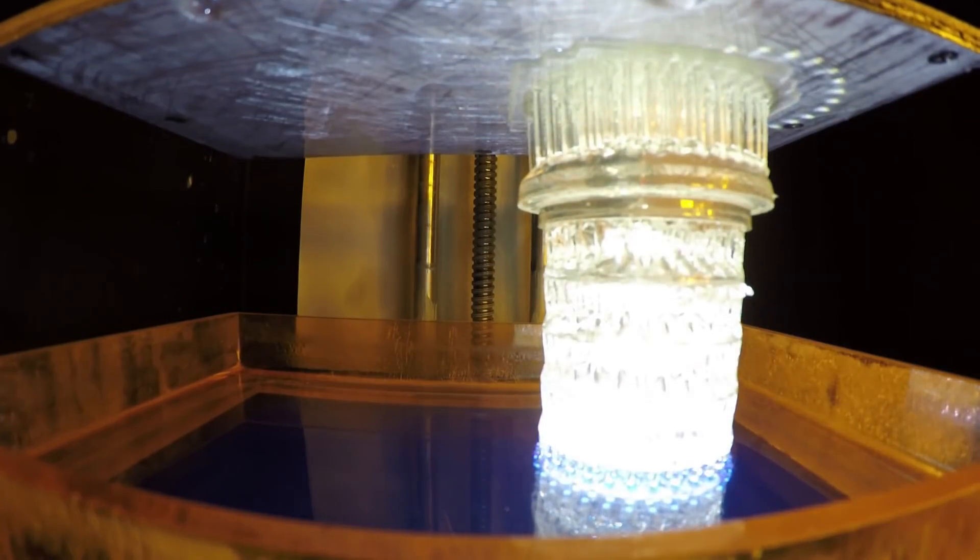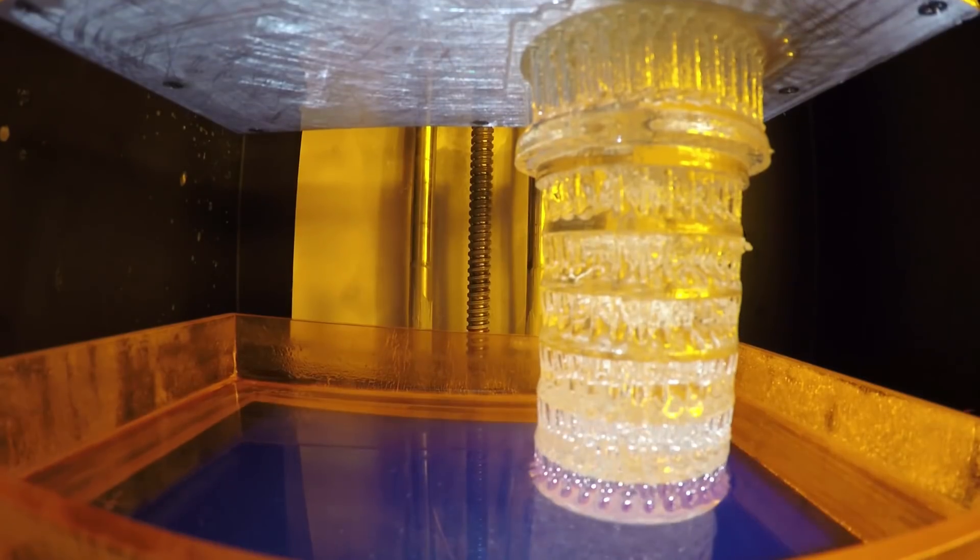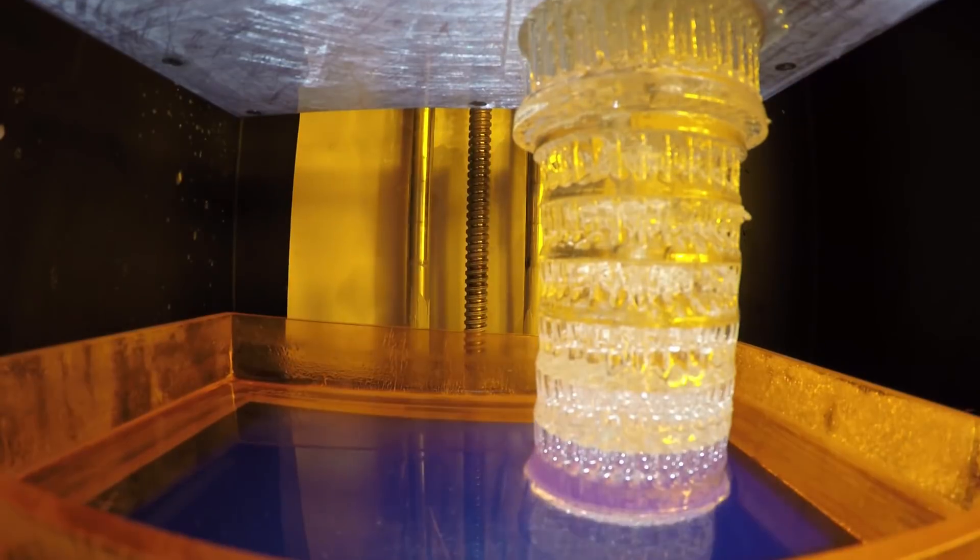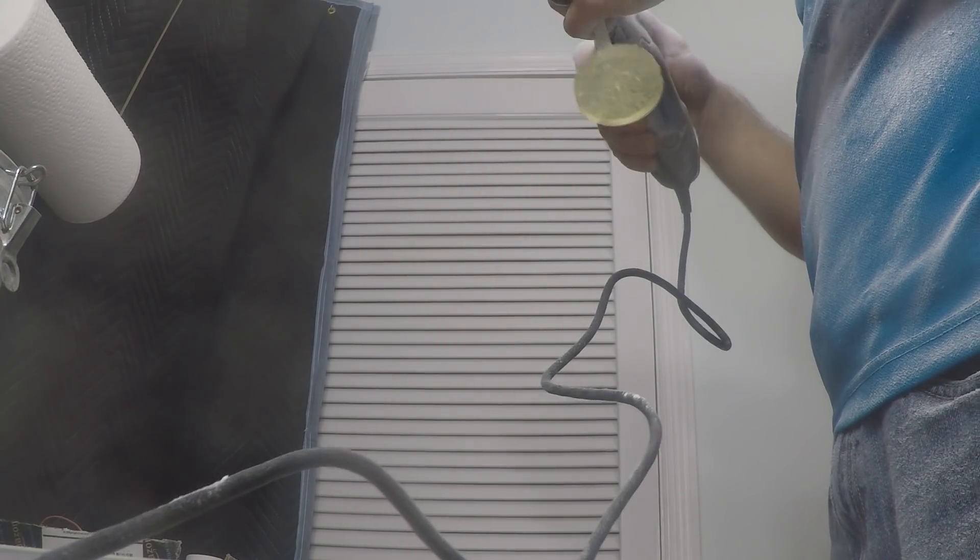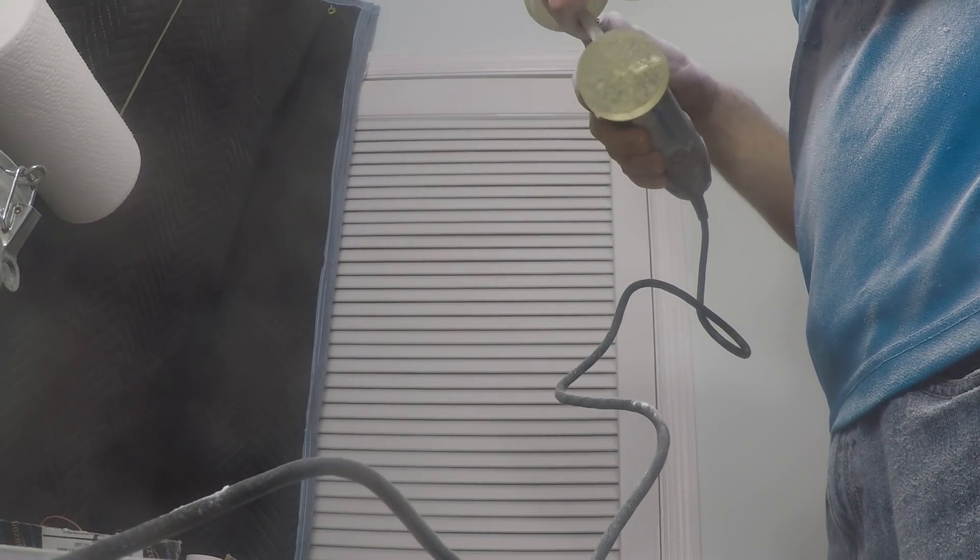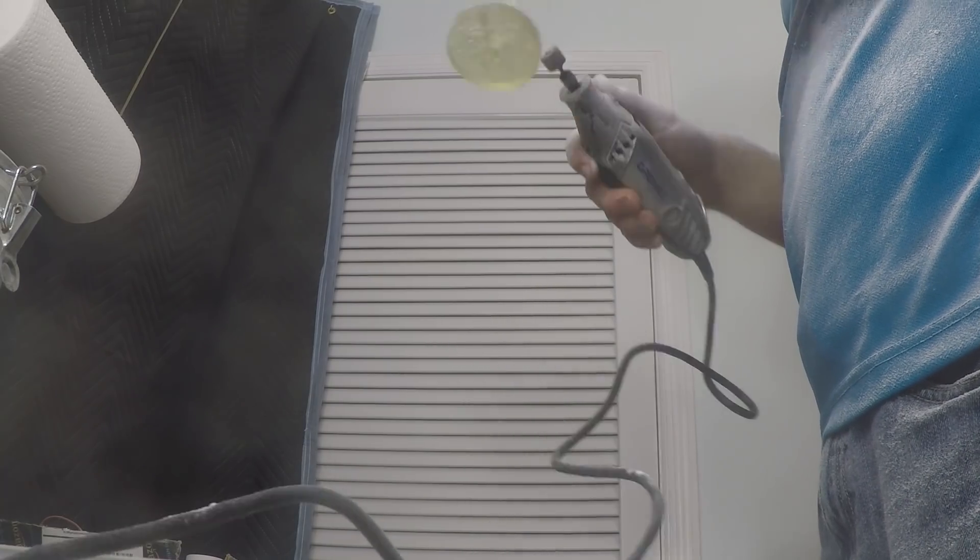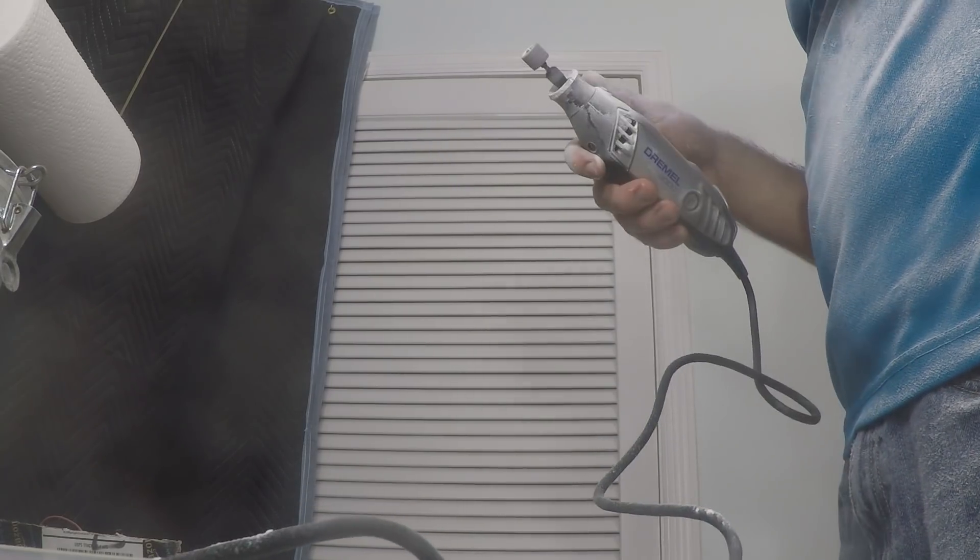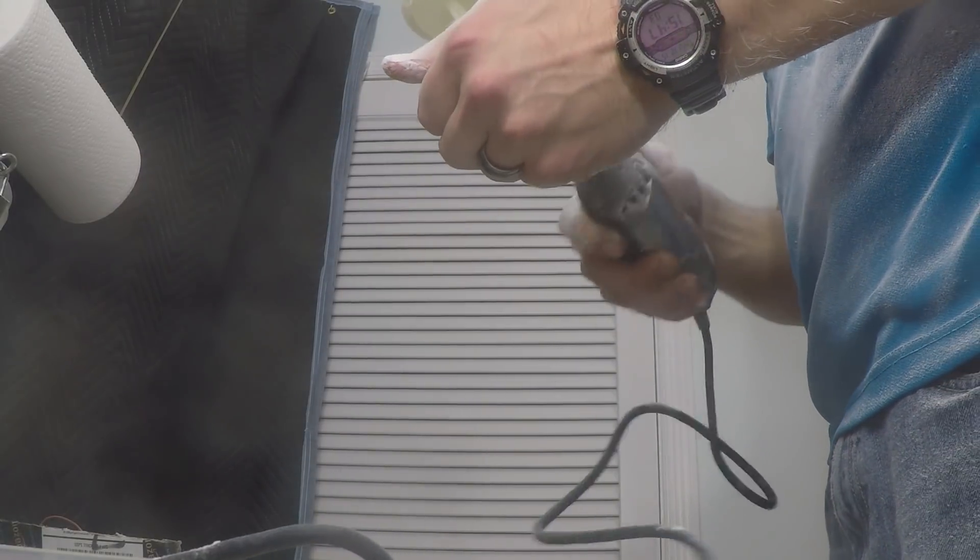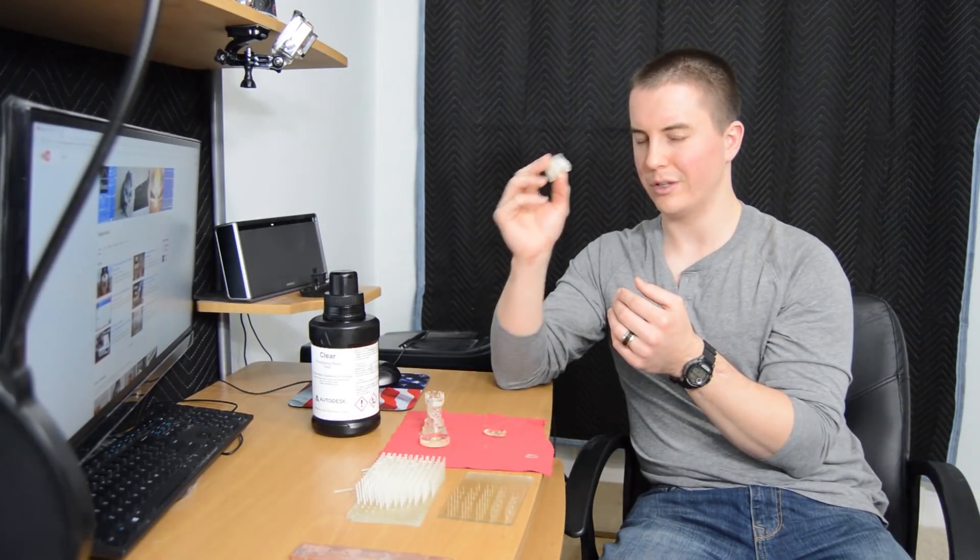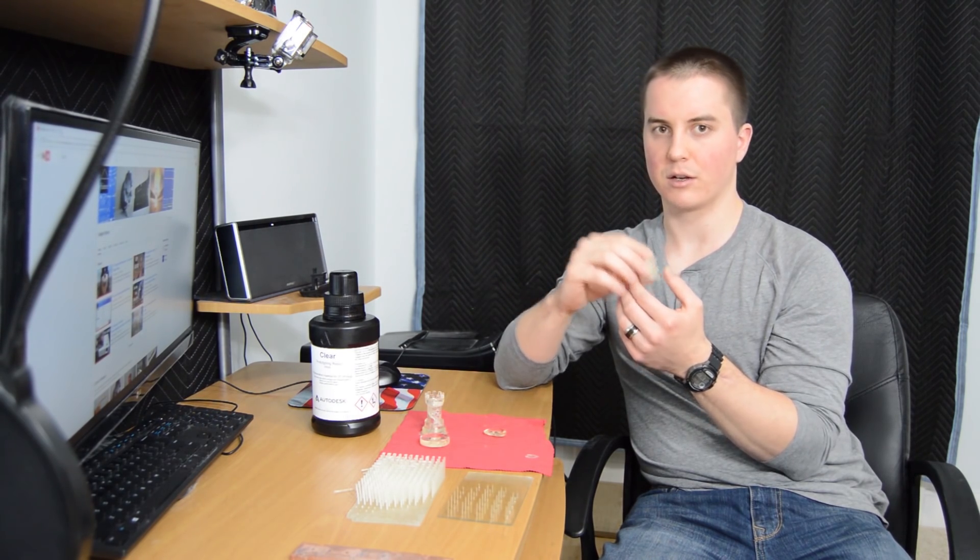It pretty much ruined the part. I had to go at it pretty hard with a Dremel to get most of that excess resin off, and there was resin dust from the sanding everywhere - it was a mess. I would highly recommend you use only maybe less than a quarter inch of resin in the bottom of your tank while you're printing and just monitor it and add a little more as needed.